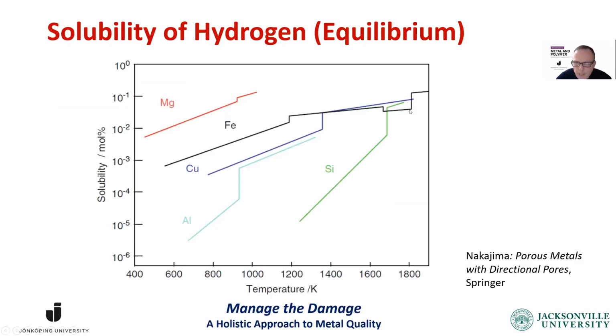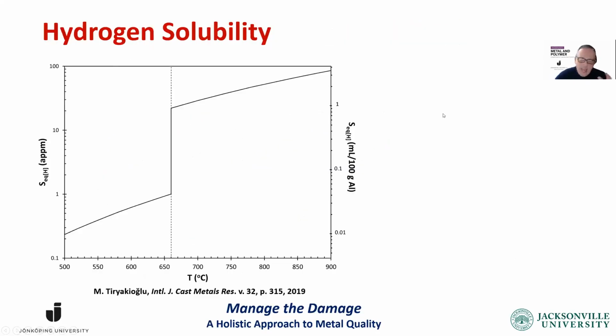First of all, the solubility of hydrogen in liquid aluminum is an order of magnitude lower than in solid iron. So we're not talking about huge levels of hydrogen. Aluminum does not like hydrogen that much. Not much is soluble. But people say it's not really the solubility level, it's the difference between solubility. This gap goes down quite a bit from the liquid state to the solid state. And there's some truth to that.